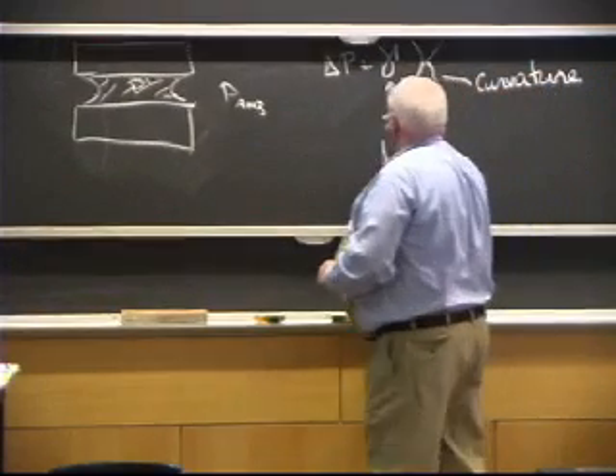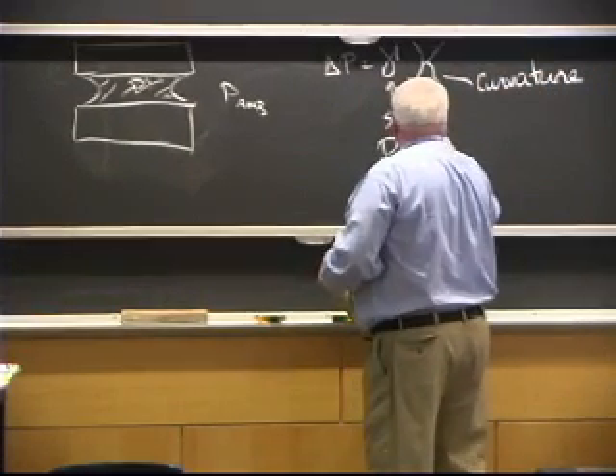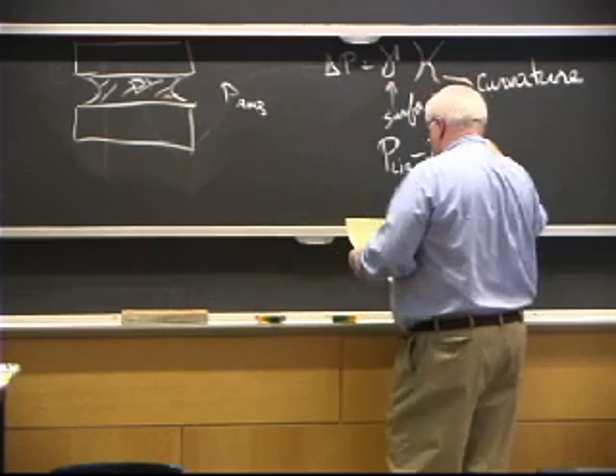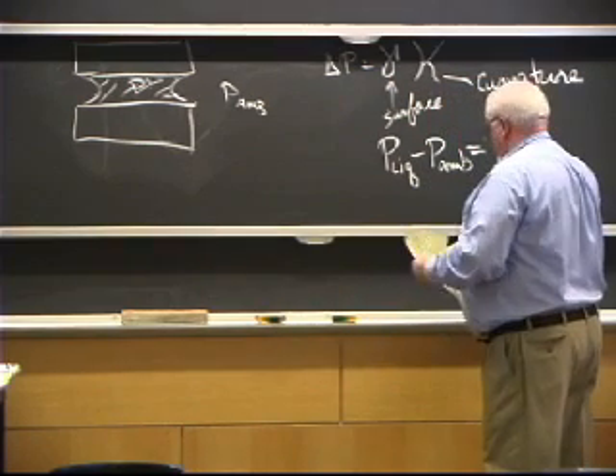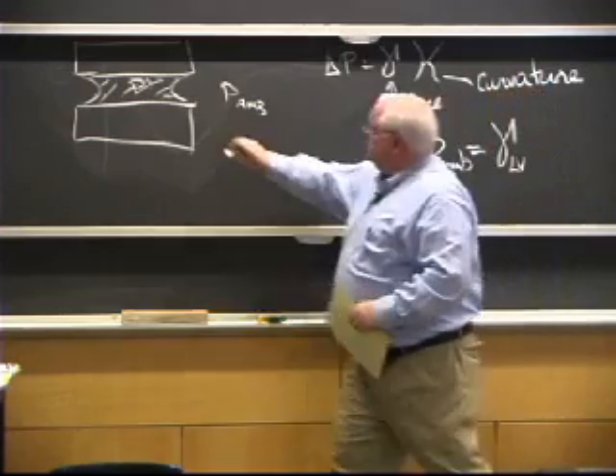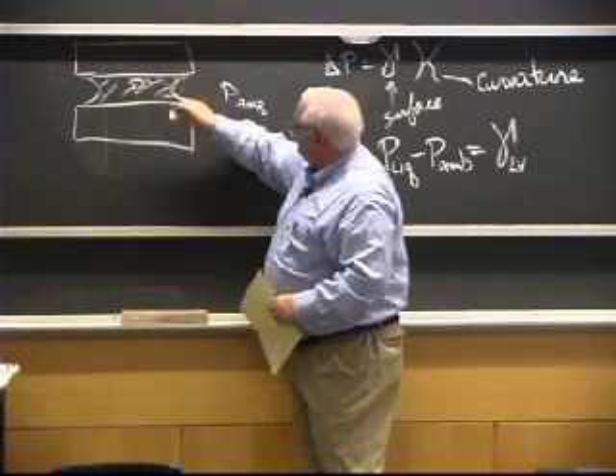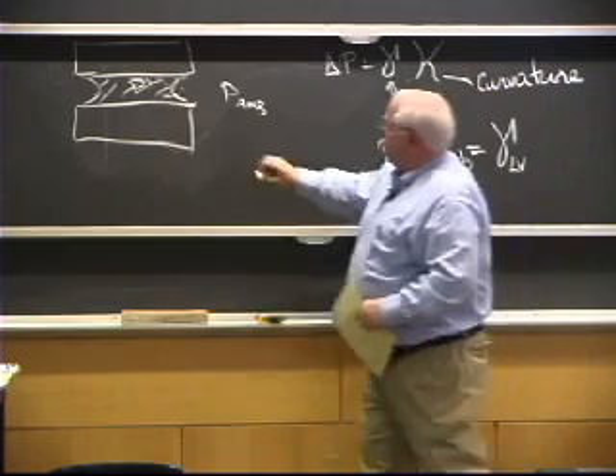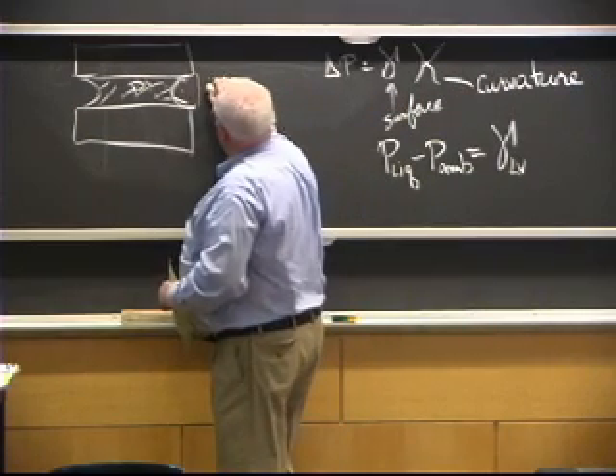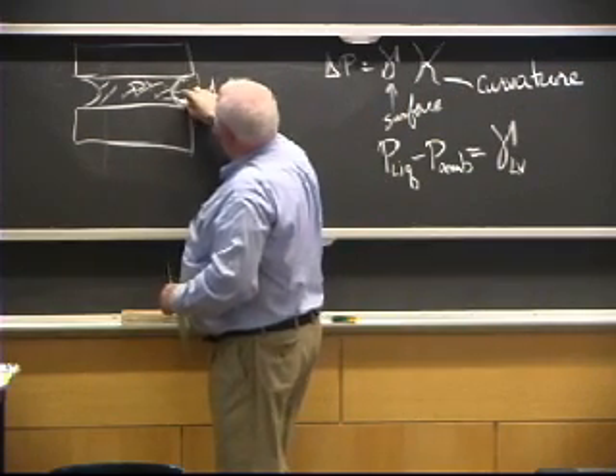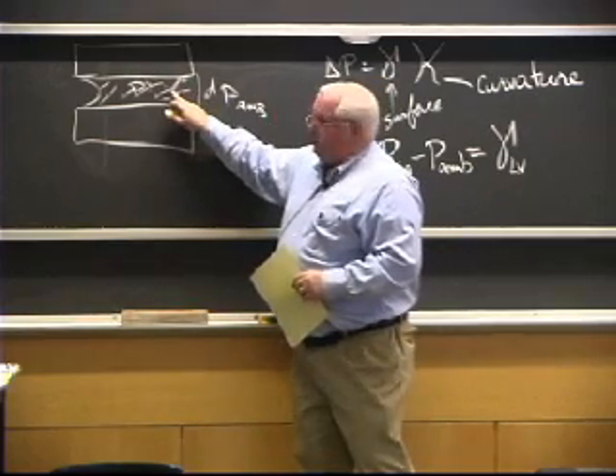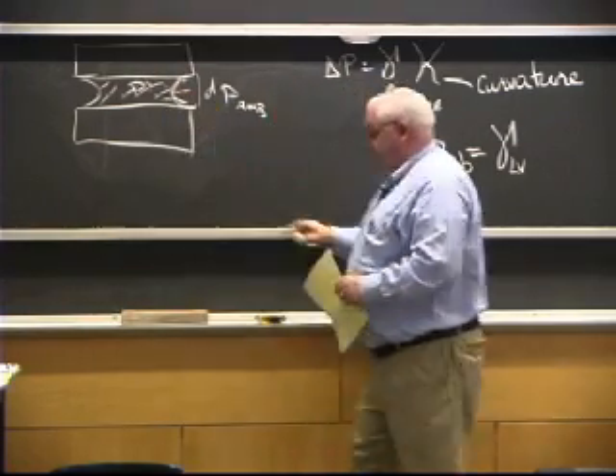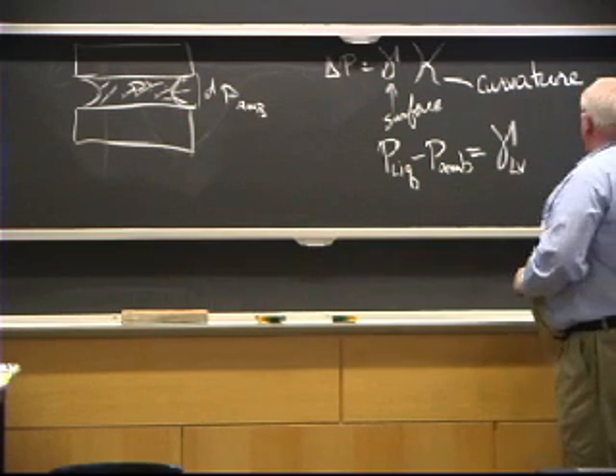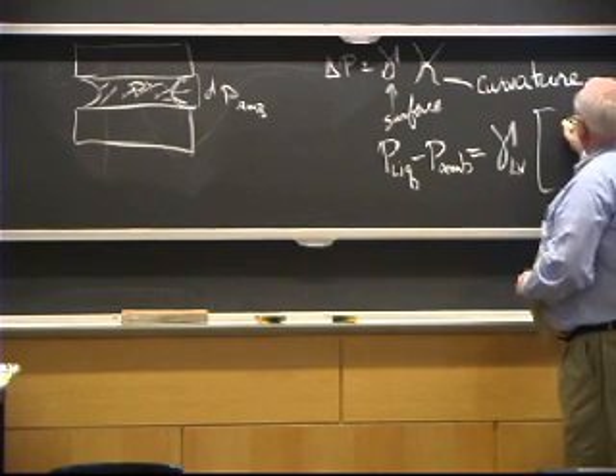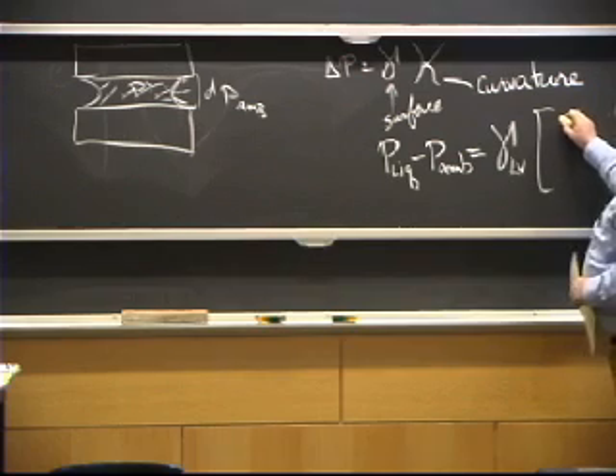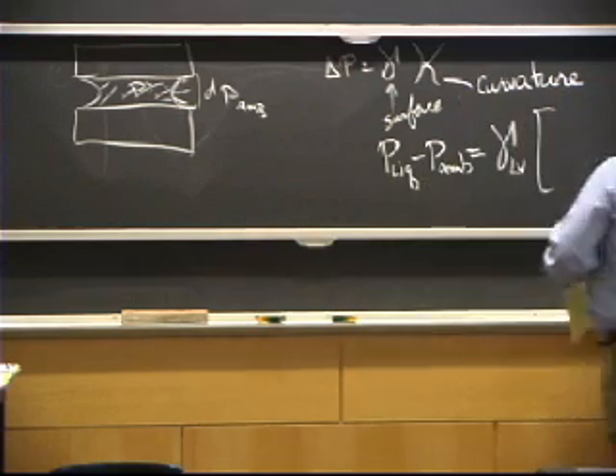And so P in the liquid minus P ambient equals gamma of, in this case, the liquid vapor interface, this surface here, because this is the curvature right here, right? And if this distance is D, and that were a semicircle, then that curvature would be D over 2, right? Or if you want to call that R, it actually is R. The curvature is 1 over R, well, let me write it over here.